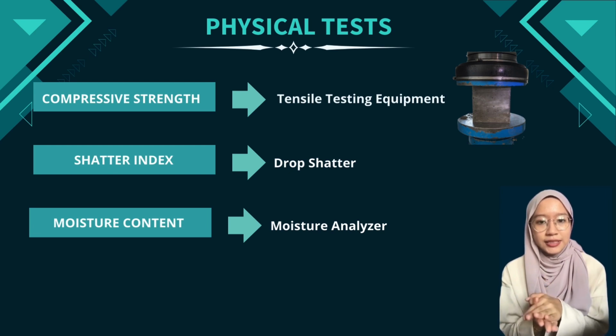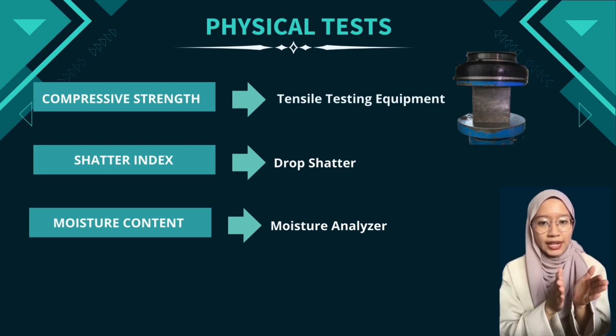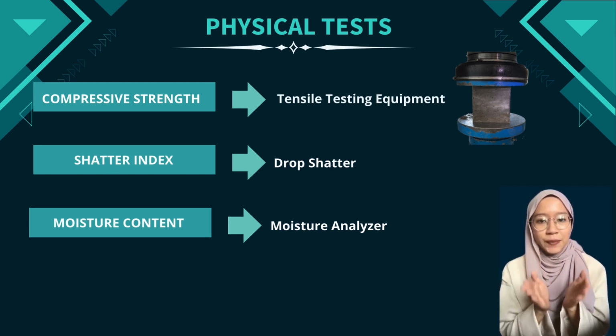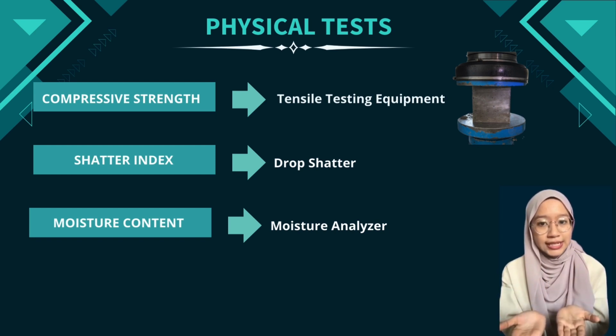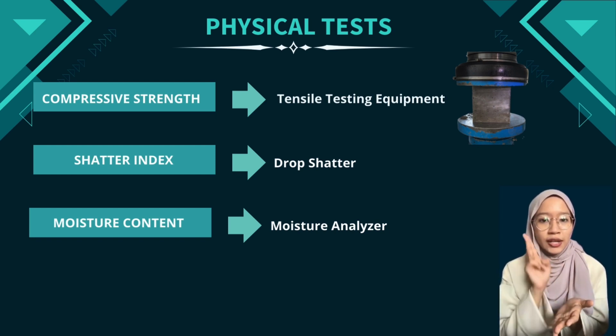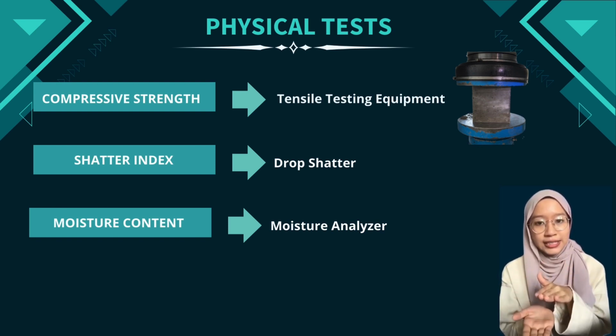The test begins by ascertaining the weight of each briquette using a weighing scale. The samples underwent a repeated dropping process, 2 times from a height of 2 meters onto a concrete floor. A charcoal briquette was placed on a designated area for the sample, and a progressively increased force was applied at a consistent rate until the sample fractured or shattered.